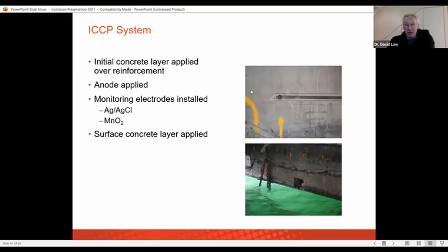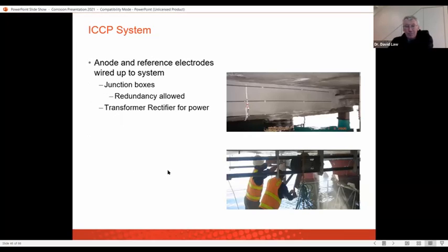You need to make sure that you put concrete over all the reinforcement before you apply the anodes, because if the anode touches the steel, the whole system will short out. So you have to be very careful of that. You put in these monitoring electrodes, and then you would put a surface concrete layer on as well to cover up your anode ribbon and your anode mesh, to make sure that's not on the surface and exposed to the environment, and it's sealed within the system.